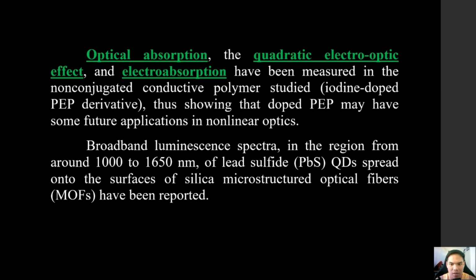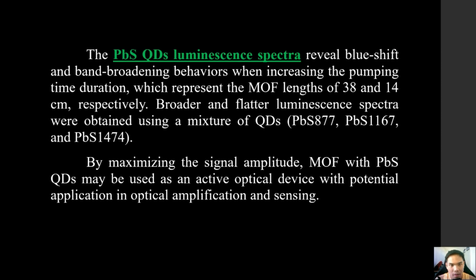Broadband luminescence spectra in the region from around 1000 to 1650 nanometers of lead sulfide QDs spread onto the surfaces of silica microstructured optical fibers have been reported. The PbS QD luminescence spectra reveal blue shift and band broadening behaviors when increasing the pumping time duration, which represent the MOF lengths of 38 and 14 cm respectively.